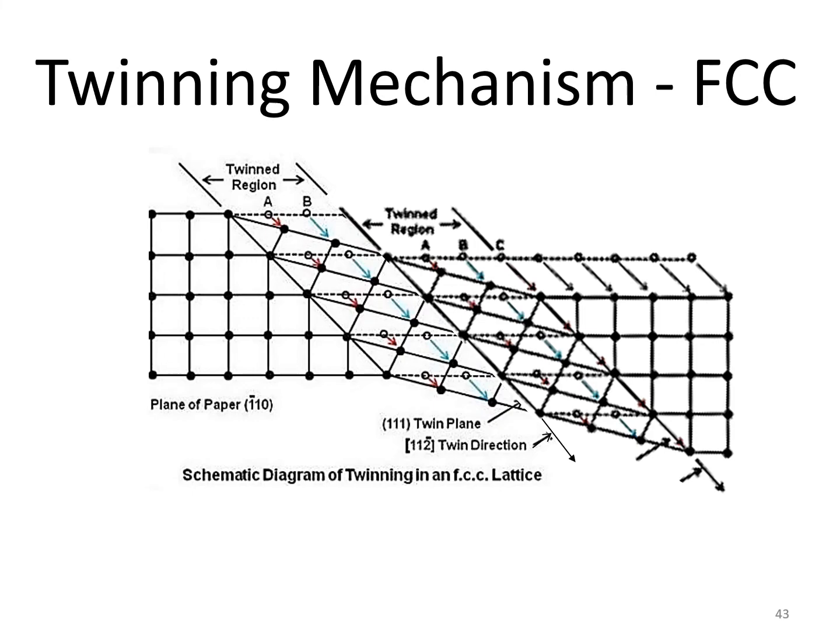It's a partial dislocation, I should point that out. But you're only moving one layer of atoms a little bit with respect to the layer underneath. So although we get this amount of deformation over here, we're shifting something from this point to this point. It's a gradual accumulation of little shears from each successive plane.